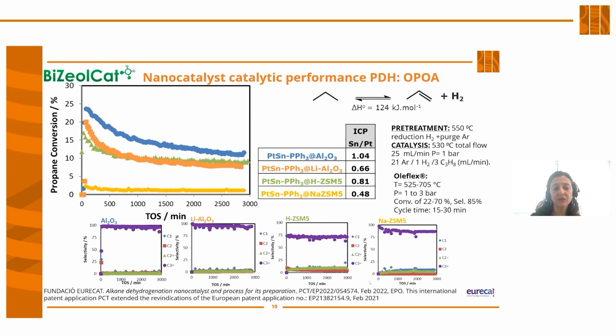And this reaction, you can see, was run for 3,000 minutes. The selectivity is very stable for the whole reaction time.